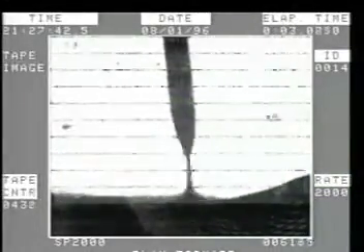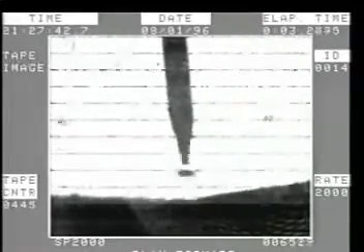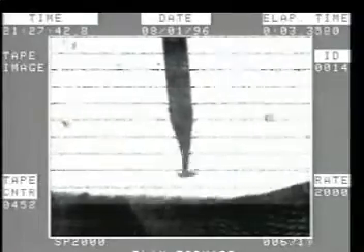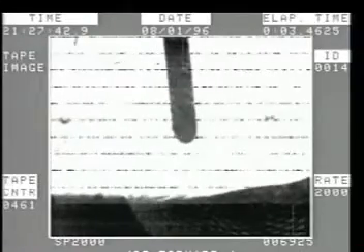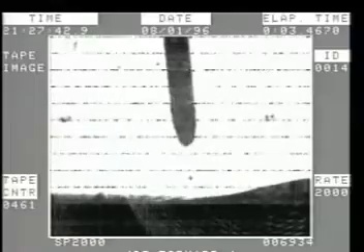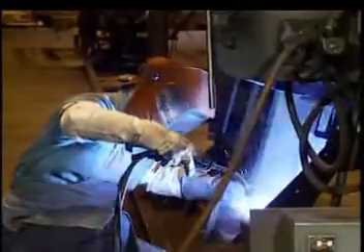Let's look at the pulse process at a higher wire feed speed. This is not pure pulse welding, rather an intermittent spray arc welding. The PowerWave power source has waveform control technology. It provides a very fast front edge in the pulse, transferring the droplets quickly. The back edge of the pulse falls at a controlled rate to add the heat input needed to wet the droplet into the puddle. Pulse spray is stable at a wide range of wire feed speeds. The process offers more advantages at both higher and lower wire feed speeds than converted axial spray. But with the waveform control technology processes, there is much more processing versatility and capability.